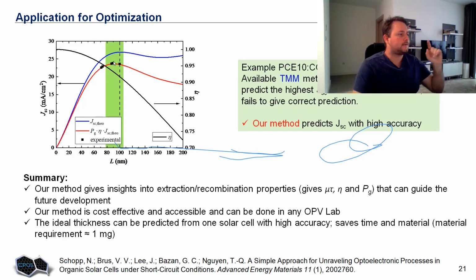And what does it tell us? It tells us that we can save a lot of time when we deal with a new blend system. Every time some chemists synthesize new organic semiconductors, we need to find the best conditions for device fabrication in order to optimize it and extract the highest performance. Usually you need to make dozens of devices, and it consumes a lot of valuable material and a lot of time. So in order to save this, by employing the technique which we propose, we can now make a single device with random thickness, for instance, 70 nanometers thickness of the active layer.